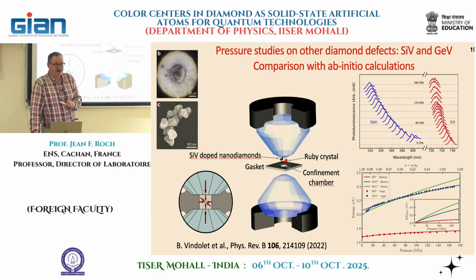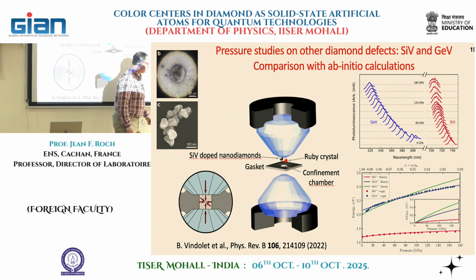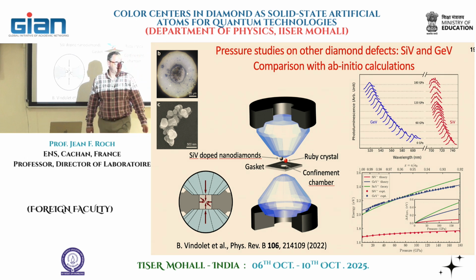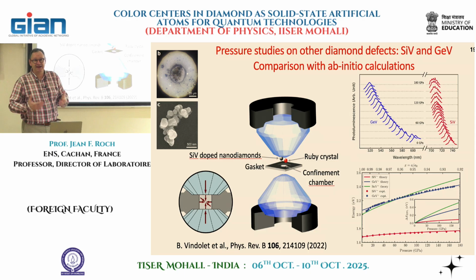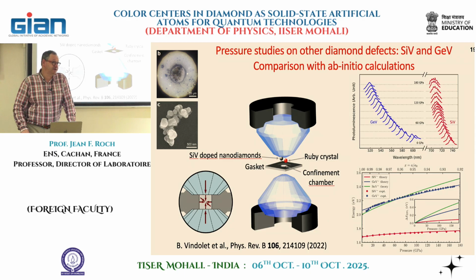But remarkably, our data fit very well with ab initio calculations that were done by Adam Gali and Lukas Razinkovas' teams in Budapest and in Lithuania. And we observed that, for instance, there is a very good agreement between the evolution of the ZPL line as a function of pressure up to almost 200 gigapascal. So this tells you that indeed we can really play now with a lot of parameters and understand, for instance, the structure of the defects, using pressure to confirm, with ab initio calculation, the structure that is observed.